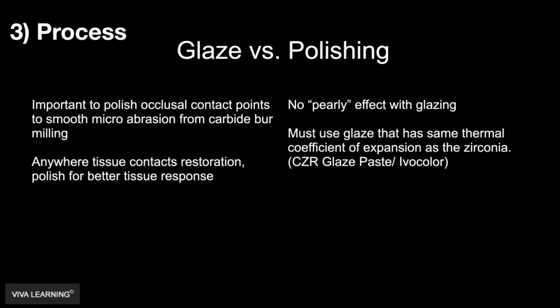Now, how do I process these once they're out of the oven? Do I go ahead and glaze them, or do I go ahead and polish them? Now, I'm using a lot of zirconia in the posterior. All of the research shows that when we polish and polish only, it actually is better for the opposing contact points. The wear that a polished zirconia crown does is the most beneficial to the opposing surface. The other thing is, when we have a polished zirconia, the gingiva likes it and responds in a much better way.